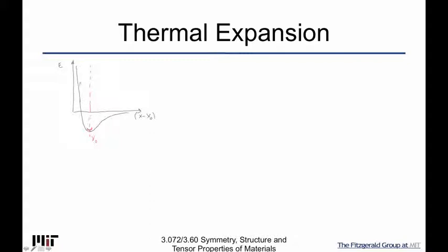A more simplistic way of saying this, which is not 100% accurate, is that it's nuclear repulsion, but that implies Coulombic nuclear repulsion, and it's actually more detailed than that because of what I just said. So there's just some very rapidly rising extra energy if you try to force two atoms too close together. And the thing pulling them in is the Coulombic one.